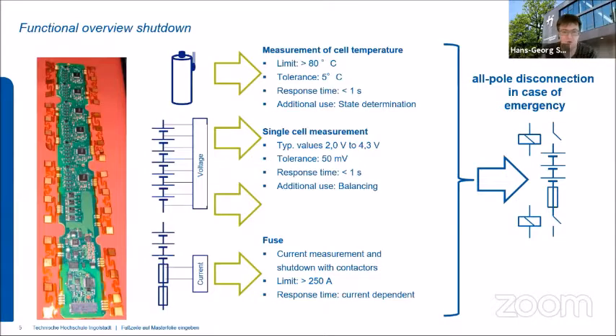The accuracies are not so important. Maybe a range of 5 degrees Celsius is enough to shut down the battery system, because you have a very broad window until a battery reacts. And it takes a lot of time until the battery enters an unsafe state. So it's not just overheating the cell 1 degree above the limit for 1 minute and it will burn down. It takes some time. So therefore you don't have to react super quick. A response time of less than 1 second is fast enough from a safety point of view regarding temperature.